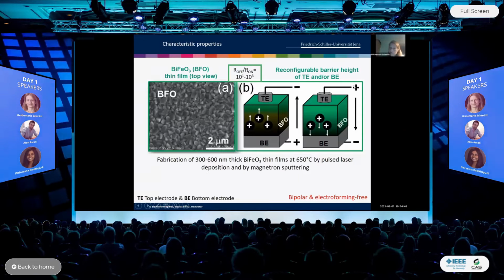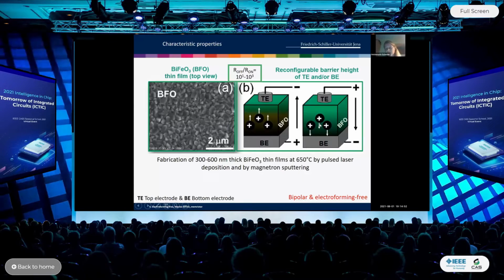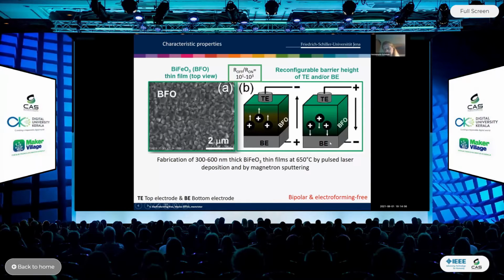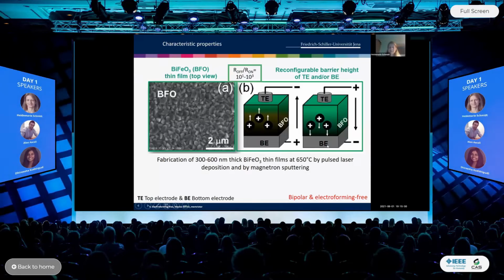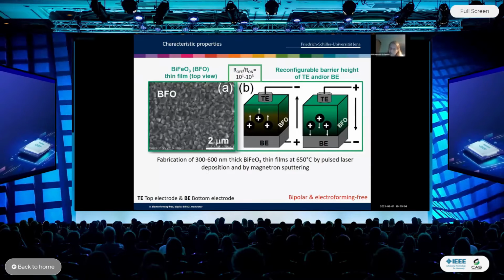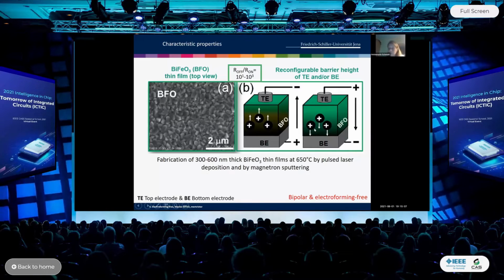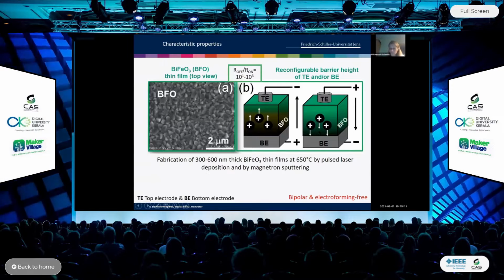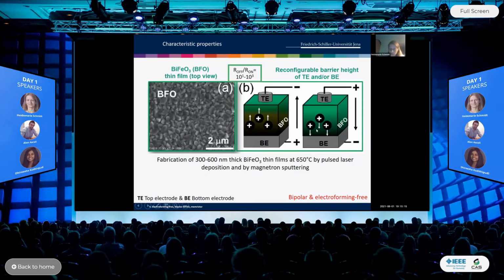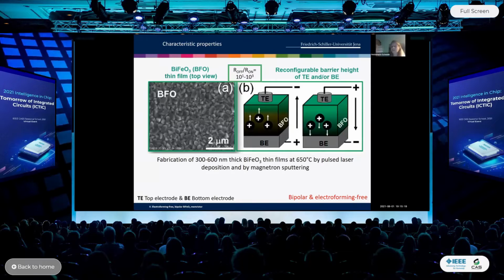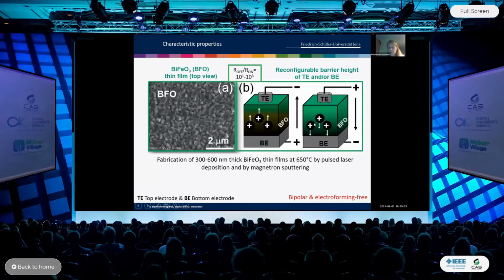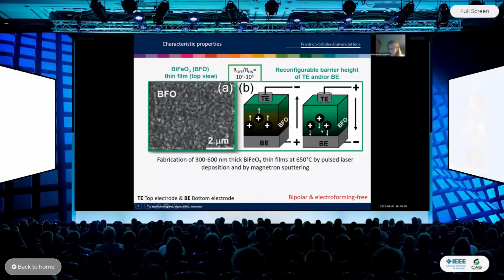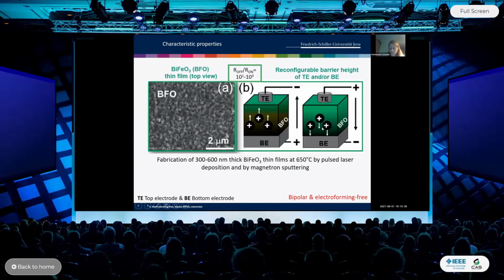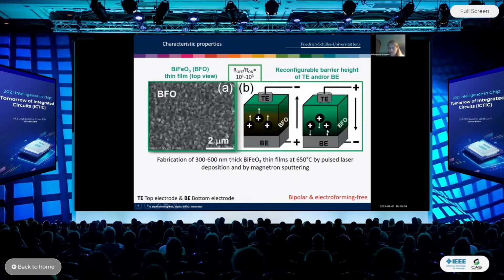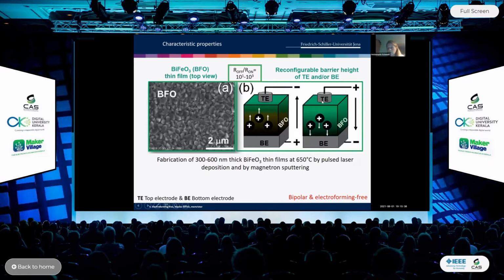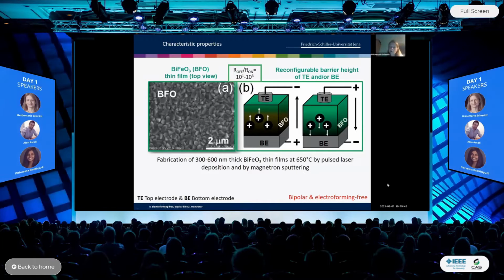On the other hand, if we apply a positive bias to the top electrode, then oxygen vacancies drift towards the bottom electrode, because they are attracted by this field, by this negative charge. And again, if we incorporate titanium traps in the bismuth iron oxide host lattice, then those traps can capture the oxygen vacancies close to the bottom electrode. And again, if we then remove the writing bias and the electric field which causes the drift of the oxygen vacancies, they are kept at the position of the bottom electrode. In this case, the bottom electrode sees a very large concentration of donors. The barrier height of the bottom electrode is tremendously reduced. It's non-rectifying. And the top electrode is getting rectifying because there are nearly no oxygen vacancies left.